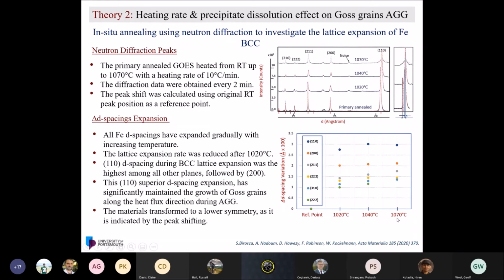Now, the diffraction pattern was obtained every 2 minutes. So this is huge data, like hundreds of diffraction patterns. What I'm showing here are just the 110 peak, the 200 peak, and a few peaks at room temperature, 1020, 1040, and 1070. Just to show, in fact, below 900 there was little change anyway. But what we try to understand is what happened during that, why the Goss grain is actually growing that much.